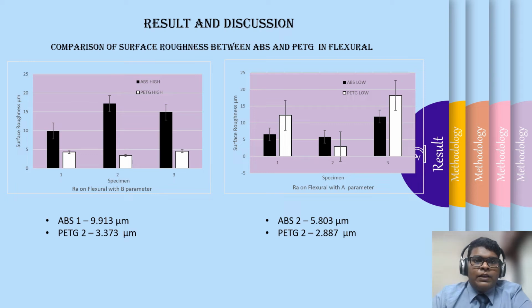Next, in comparing the surface roughness of flexural, using the high-level parameter, PETG has the smoother surface finish than ABS. This can be proven by the graph above, where the PETG doesn't cross the value of 5. Using the low-level parameter, ABS has the smoother surface finish compared to PETG.